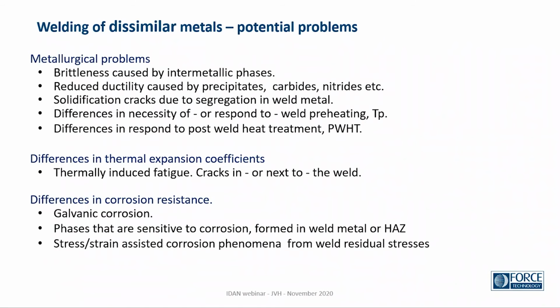We see differences in thermal expansion coefficients, which might lead to thermally induced fatigue. And it's not a problem during welding, but in the applications afterwards. If temperature is going up and down, the two parts don't follow each other exactly, and we might get cracks in the weld or next to the weld, depending on what is the weakest point.